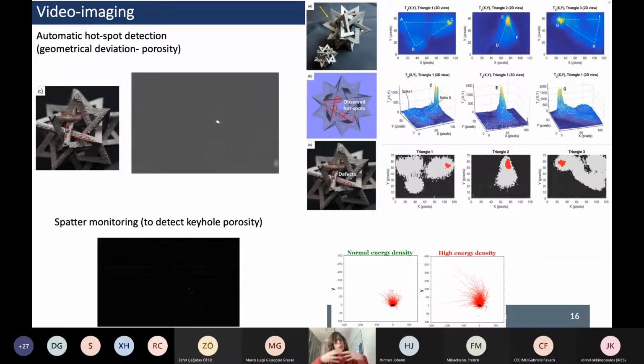So if you can see the signature of the spatters coming out from the melt pool, we saw that this spatter phenomenon can be linked to some sort of over melting or under melting that at the end results in porosity, lack of fusion or over melting porosity. Just looking at the spatter signature. So just looking at some sort of idea of what is coming out from the melt pool.